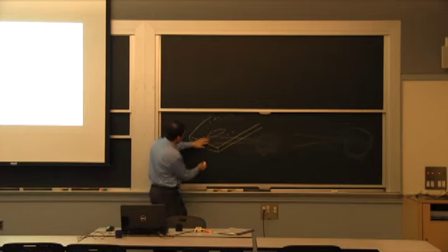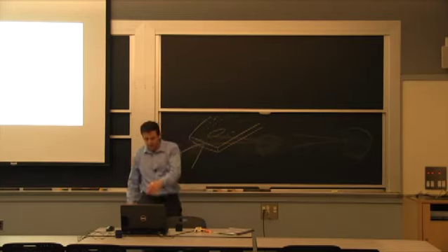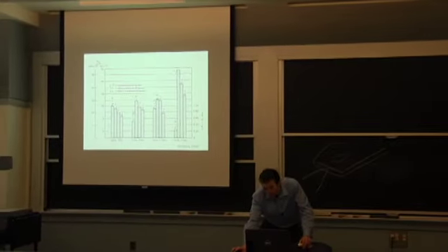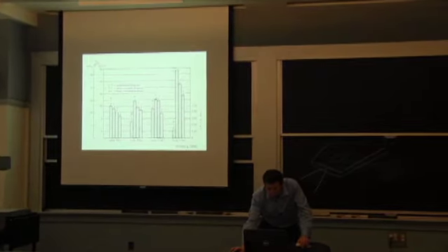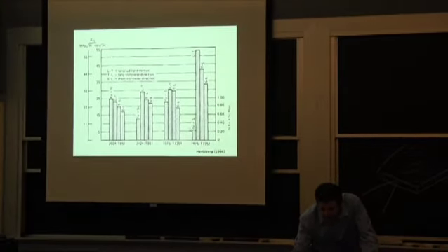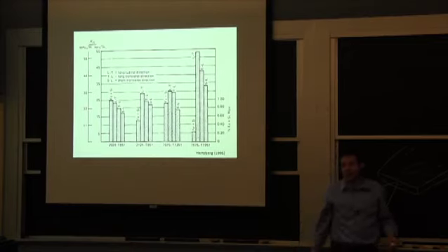And therefore, if you have a crack that is going this way, trying to separate and open it up, it's a lower resistance. And that's what those plots show here for the ST direction. You have about 30% less fracture toughness. The first column for each of these four alloys is the iron and silicon content. It gives you an idea on how many inclusions you have.